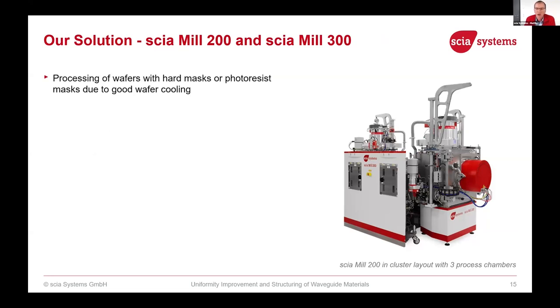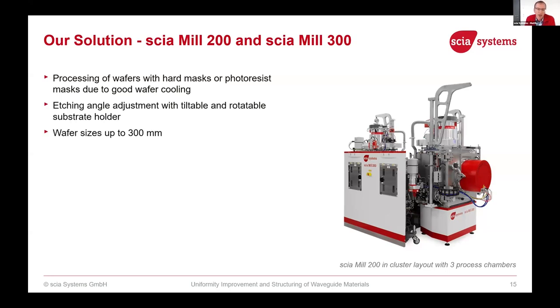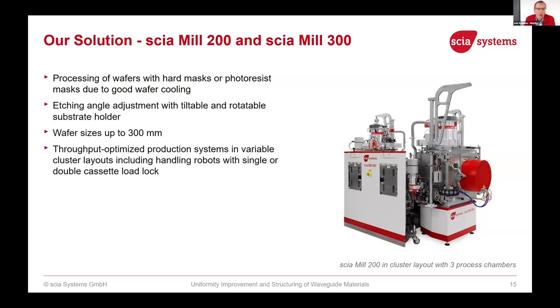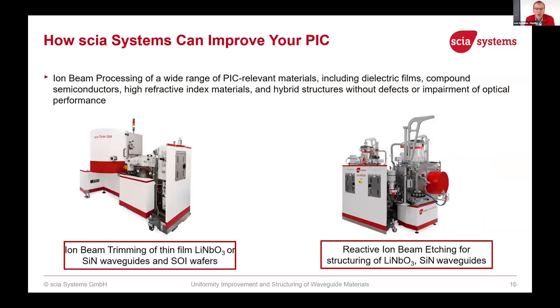You see here the picture of the version with 3 process modules and 2 load locks, so high volume manufacturing ready. We can process wafers with photoresist masks or hard masks. We have good cooling. The etching angle can be adjusted with a tiltable and rotatable substrate holder, as mentioned before, up to 300 millimeter. I also mentioned we optimized the system for high throughput with that robot system and multiple modules. And we have also versions as a flexible tool for R&D and startup companies with just a single load lock available. And this brings me to the summary.